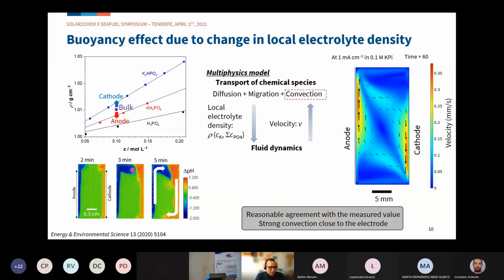We also measured the velocity of the electrolyte. We can see strong convection close to the electrode because this movement is caused by electrochemical processes. This is important because this is the region where we have the pH gradient.